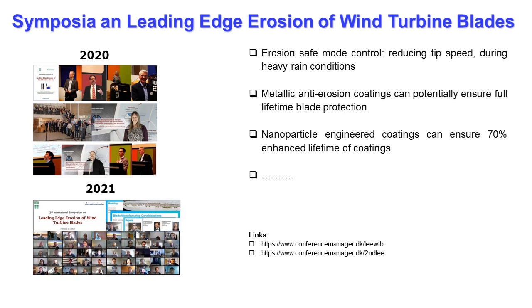Metallic anti-erosion coatings, which are developed by the British Offshore Renewable Energy Catapult, can potentially ensure full lifetime blade protection. Nanoparticle engineered coatings, for instance with graphene, can ensure a 70% enhanced lifetime of coatings. Better adhesion of coatings should prevent their delamination. There are several concepts on how to prevent blade erosion, and many groups work on them. We expect to see new results in the coming months and years.